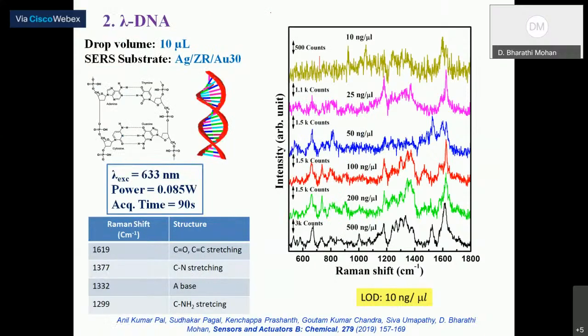And then we also tested with lambda DNA with a drop volume of 10 microliter. And in this case, we used gold-based hybrid nanostructure. The wavelength of the laser light was 633 nanometer, and the power that we applied was 0.085 watt, and acquisition time is 90 seconds.